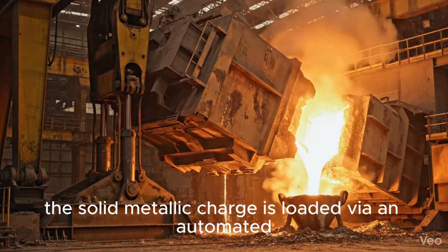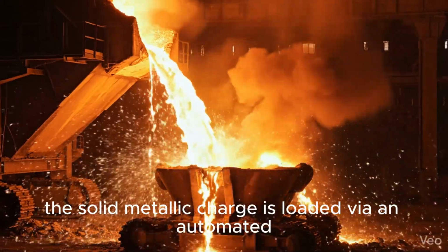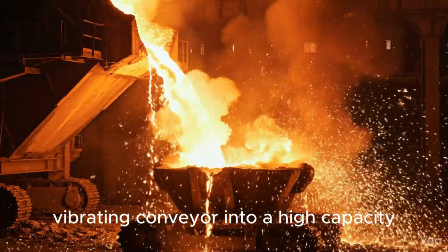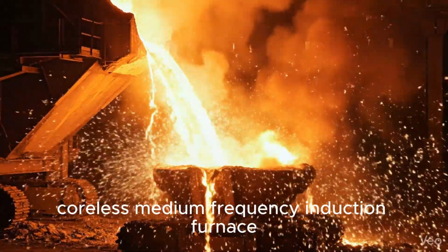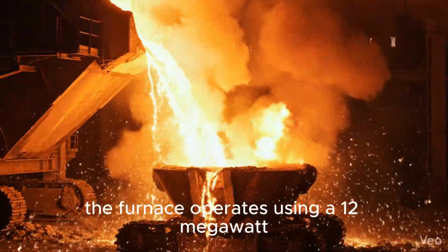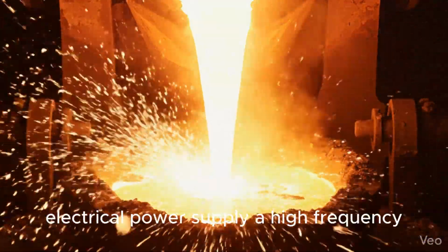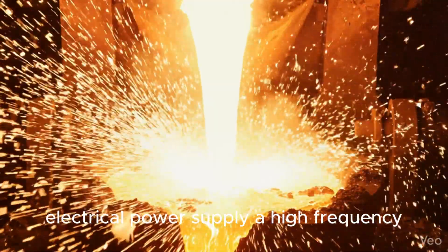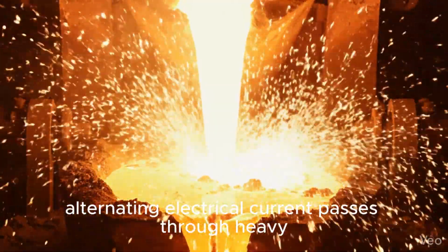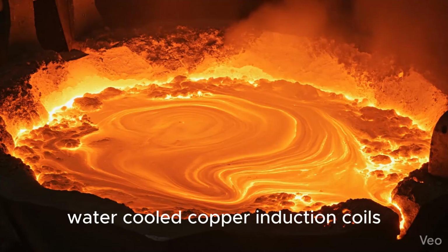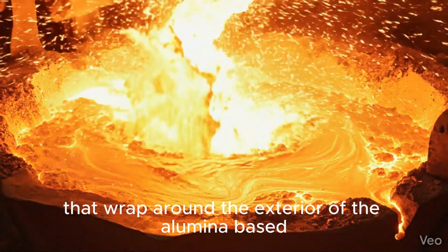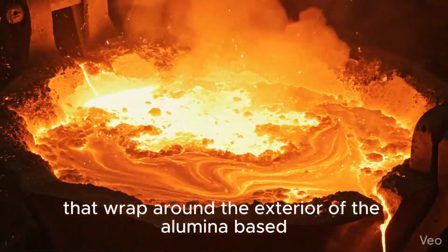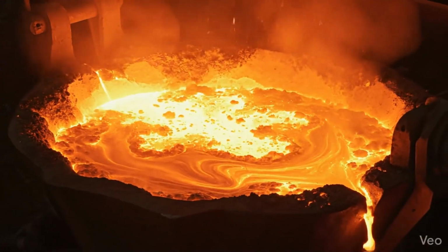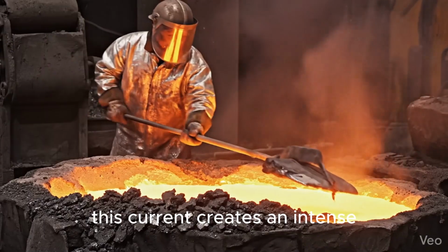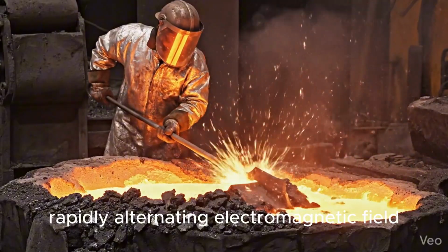The solid metallic charge is loaded via an automated vibrating conveyor into a high-capacity coreless medium-frequency induction furnace. The furnace operates using a 12 megawatt electrical power supply. A high-frequency alternating electrical current passes through heavy, water-cooled copper induction coils that wrap around the exterior of the alumina-based refractory crucible. This current creates an intense, rapidly alternating electromagnetic field.